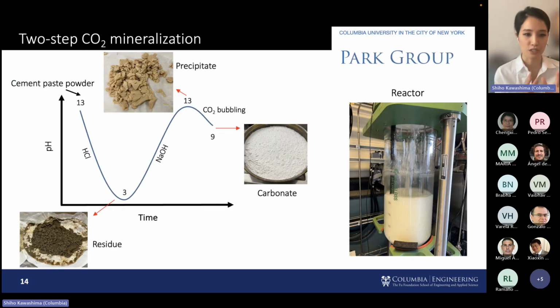Okay, so this is actually looking at what the process looks like. You start off with this recycled cement paste powder, and then you drive down the pH, and then you extract out your calcium, and then you have this silica-rich residue left over. So that is our candidate SCM.